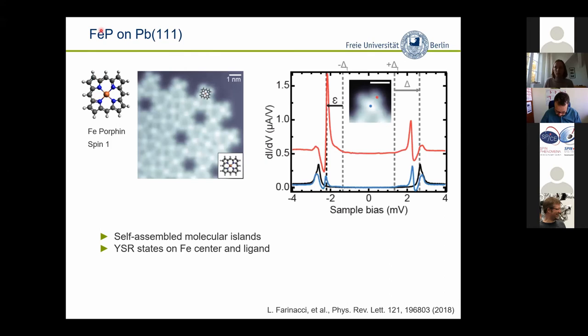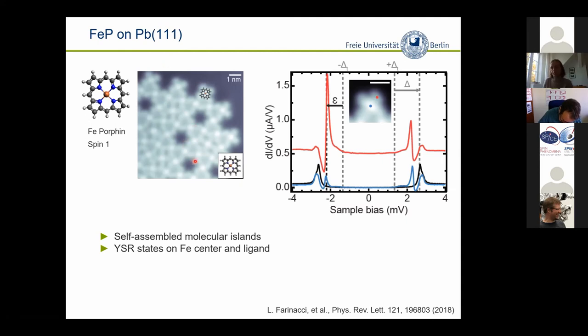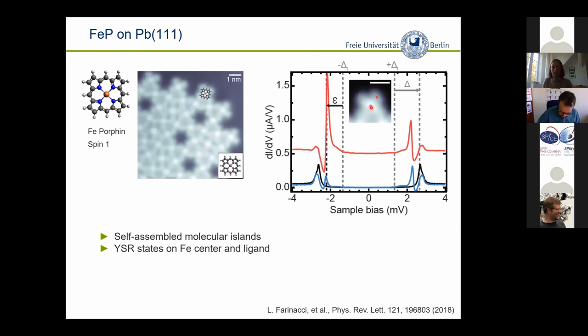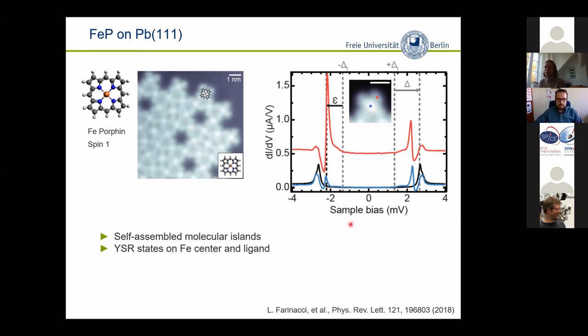This brings me to two topics: changing the exchange coupling strength and tuning through the quantum phase transition, and looking at how potential scattering or the density of states affects the Shiba-Rusinov states. The first one involves a molecular system on lead — an iron porphine molecule on a lead surface. It's iron porphine: you have an iron center embedded in an organic skeleton with nitrogen atoms that impose a crystal field. You deposit these molecules on a lead (111) surface, which is superconducting, measured at 1 K. They self-assemble in densely packed islands.